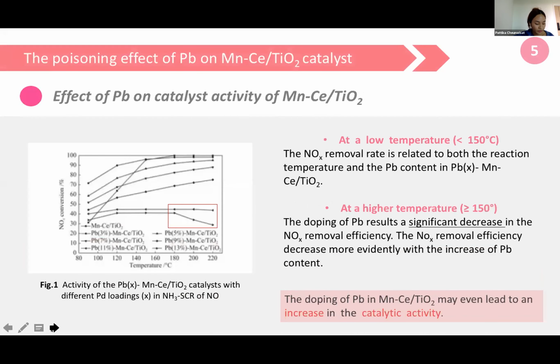The figure shows the activity of the Pb manganese cerium titanium dioxide catalyst with different Pb loading. At a low temperature, less than 150, the NOx removal rate increases with both the reaction temperature and Pb content. At a higher temperature, more than 150, the doping of Pb results in a significant decrease in the NOx removal efficiency. The NOx removal efficiency decreased more evidently with the increase of Pb content.